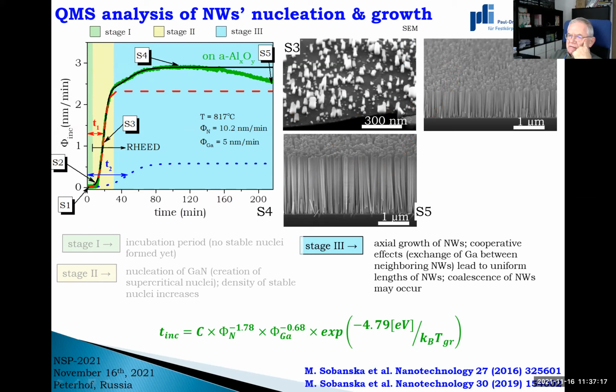Okay, what's important in the story is that this green profile that we have here, we can fit using an analytical formula. I'm not giving this formula right here because it's boring, it's not important for the topic. But we have an analytical description of this profile, and by fitting this equation to the experimental profile, we can measure in particular the value of the incubation time. This is the time needed in QMS, defined in such a way that more or less half of these islands are created already, and we get this value from fitting.